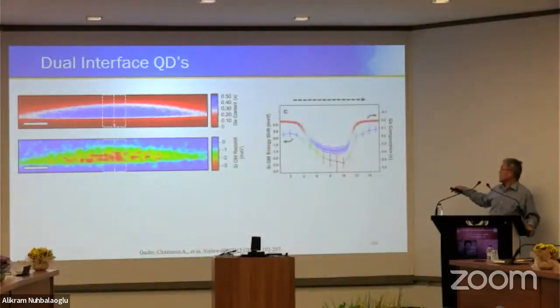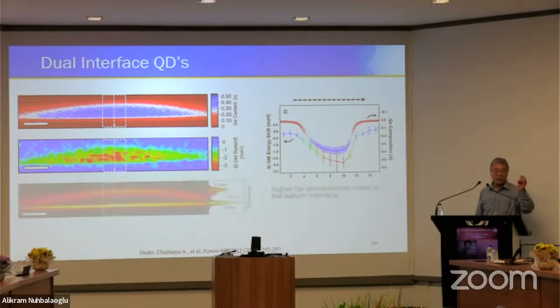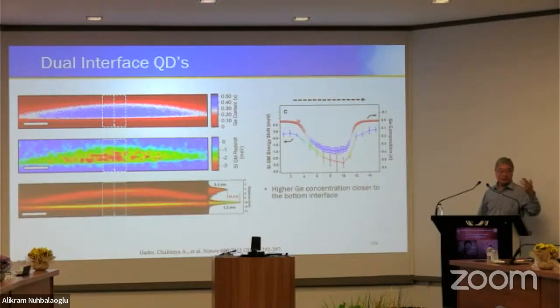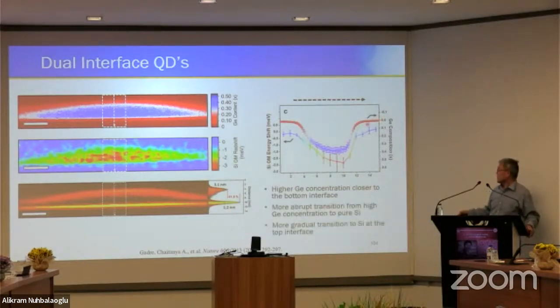But most important, we see that the energy shift of the mode is consistent with the change of the silicon germanium ratio. That means if you change the chemistry, you change the energy of the phonon. Okay, that is straightforward because of that, right? Okay, that is not surprising.